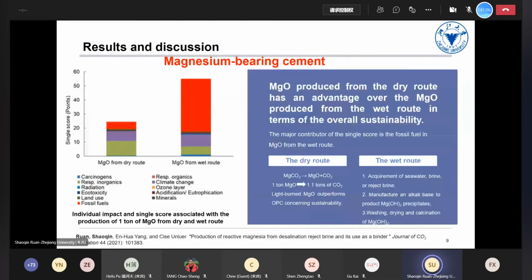And the second part is about the magnesium-bearing cement. First, I will briefly introduce MgO, because MgO is the major component used in magnesium-bearing cement. Magnesium oxide is produced from the dry route. The dry route is the calcination of magnesite, and as you can see from this equation, it produces magnesium oxide and carbon dioxide.